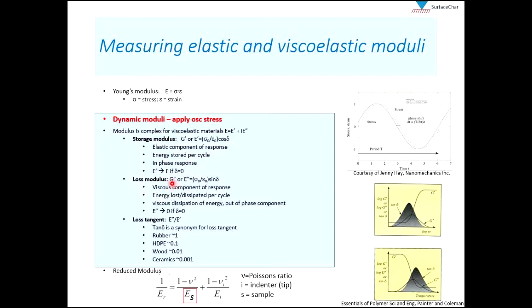Now, the loss modulus is termed either G double prime or E double prime, and that's equal to the initial stress over strain times the sine of the lag. The loss modulus is the viscous component of the response and refers to the energy lost or dissipated per cycle. And note that it goes to 0 if this lag is 0. Now, the final viscoelastic property is called the loss tangent, and that's simply the loss modulus over the storage modulus, the ratio of the two. The loss tangent is probably the most empirically useful, especially in the polymer community. Tan delta is a synonym for loss tangent.